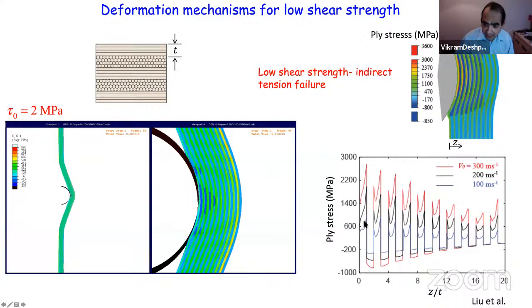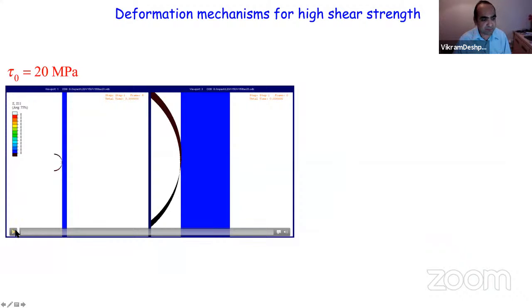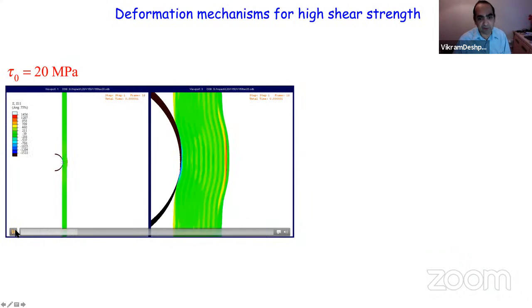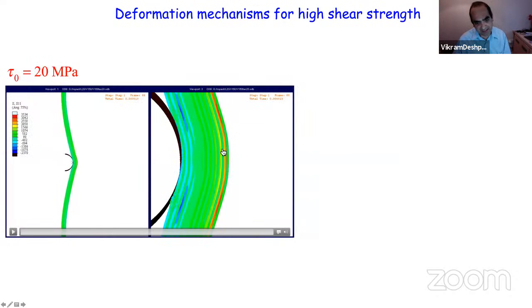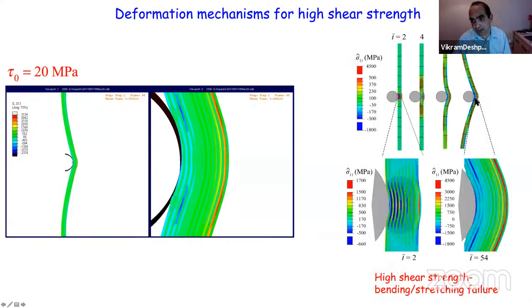If you plot the ply stress underneath the beam as a function of the depth of the beam, you can see that you really need to model every ply discretely here, because you go from one ply being in tension to the next ply in compression and then to tension, etc. So there's an enormous inhomogeneity that has developed because of this indirect tension mechanism underneath the projectile. And if you go to high shear strength beams, something completely different happens. You completely change the mode of deformation and you get very high stresses at the back, and you're going to get failure at the back of the beam. And that's what happens in traditional carbon fiber composites.